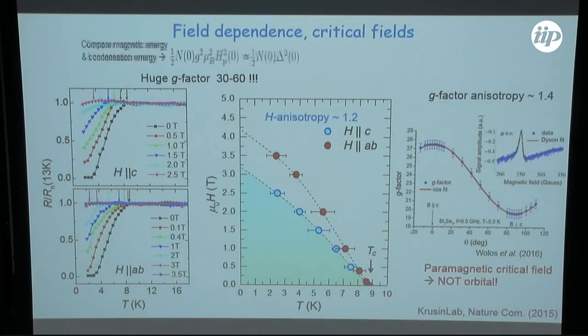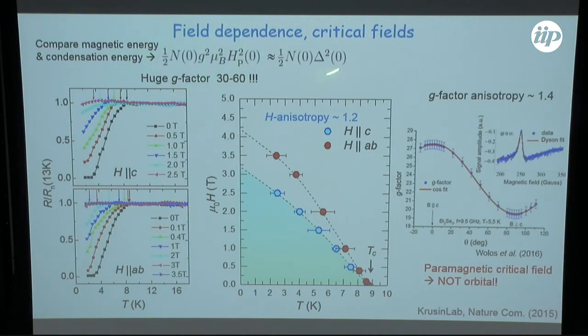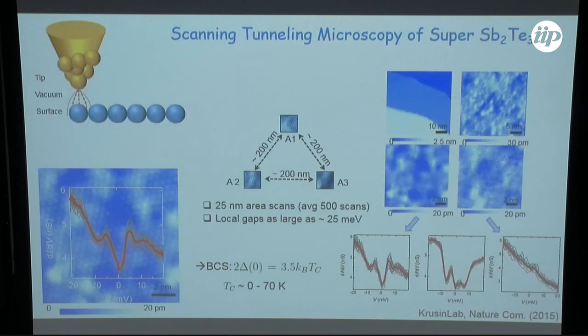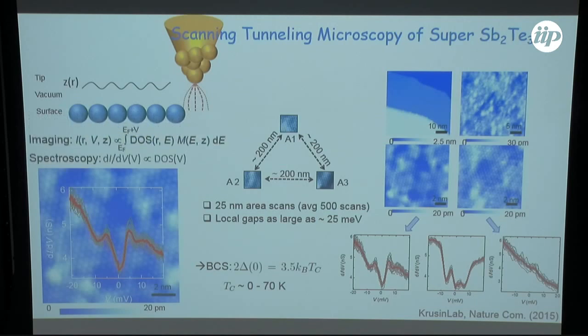In fact, if you do a back-of-the-envelope estimate and calculate TC from here, because of this large g factor you would expect that TC would not be 10, but around 60. So at first we were really puzzled by this. What we came to, and something that was confirmed in STM measurements, is that we actually have a distribution of gaps. This is the STM data from Abe, and I'm not going to go through it in detail. You can read it in the paper, but the key is that if you just do the simple BCS estimate, TC should be, locally, anywhere between 0 and 70 Kelvin. At least in these measurements, local gaps are as large as 25 milli-electron volts.